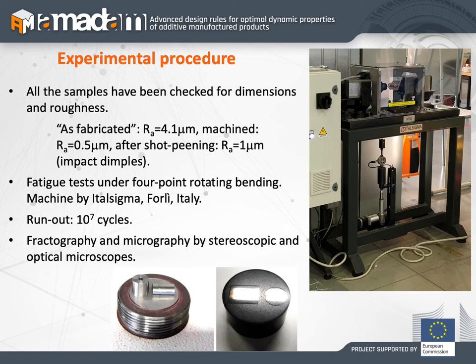The testing machine is a rotating bending machine, a typical Moore machine that we have at our lab. We can control, obviously, the loads and the number of cycles in a semi-automatic way. We have also measured the roughness of the specimens, and here you can see that in the case of as-fabricated specimens, we have a roughness of 4.1 micrometers. When we machine the specimen, we reach 0.5 micrometer of roughness, and after the peening, we have a roughness of 1 micrometer. So the micro shot peening, due to the impact, produces a higher roughness.